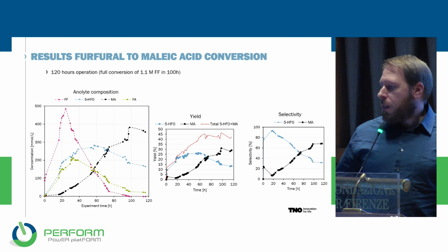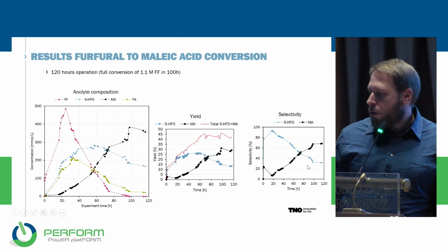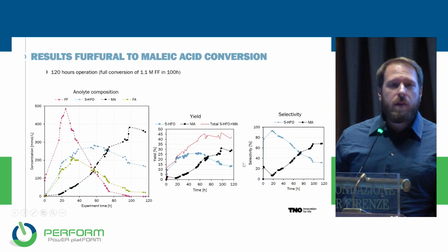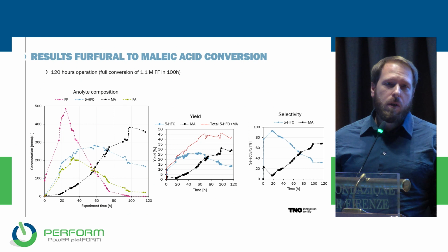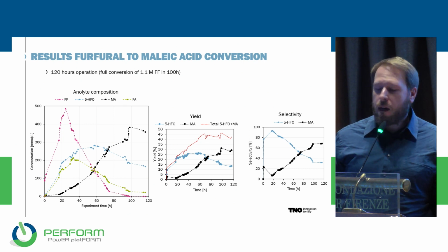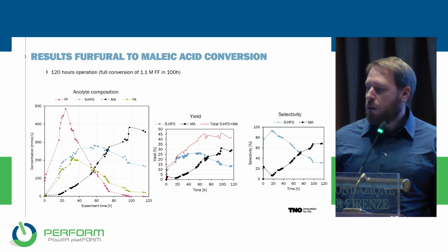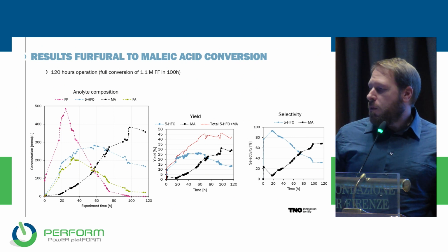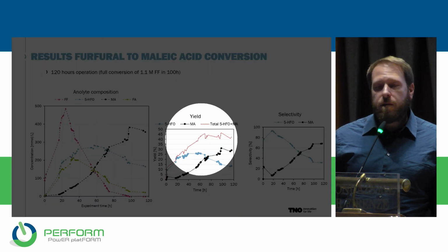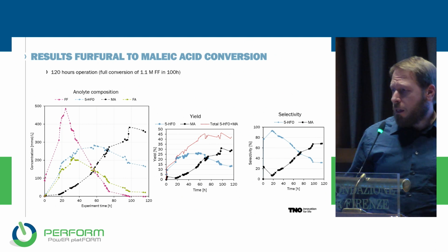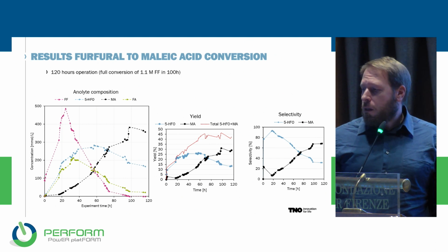We can look at the selectivity. This is also a reflection of what I just said. At the beginning of the reaction, we only make 5HFO. Only when we run out of furfural, we start to make maleic acid from 5HFO. If you look at the yield, in this case, we can combine the yield of maleic acid and 5HFO. And well, here the yield is quite decent.